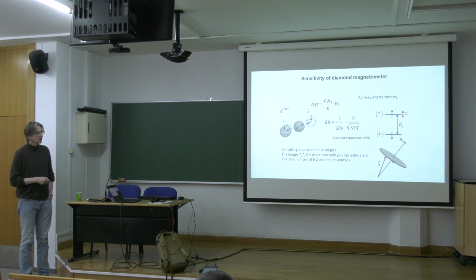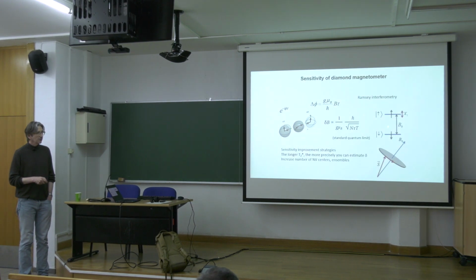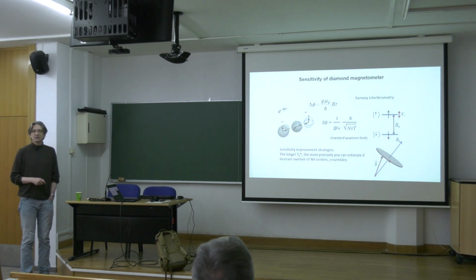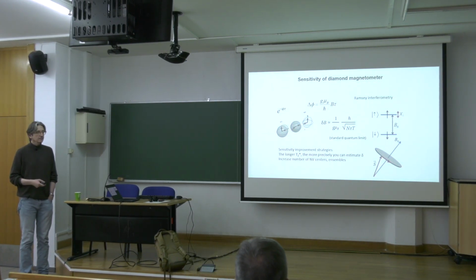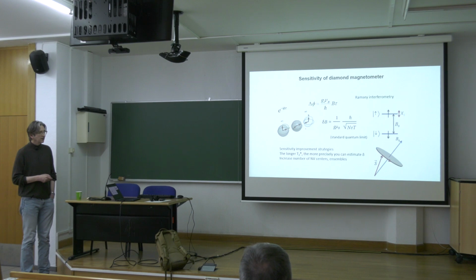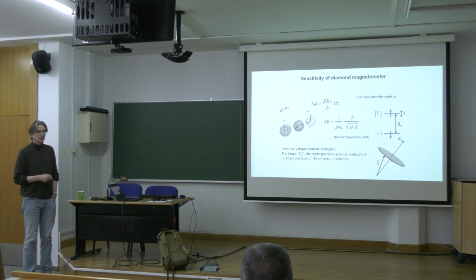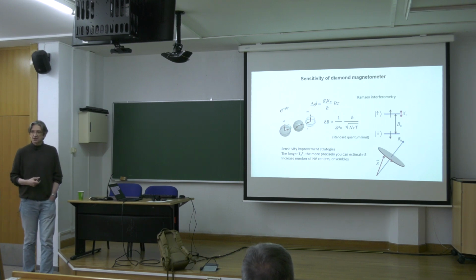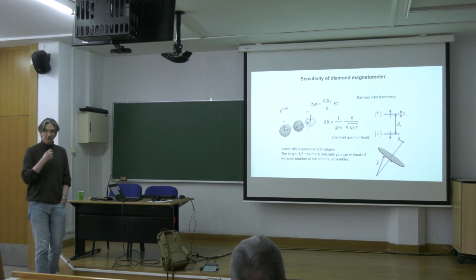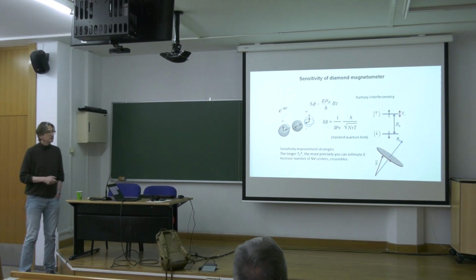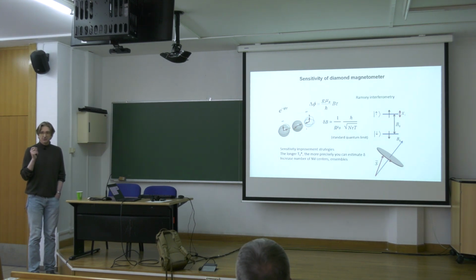So the experiment we do here for magnetometry as a model is exciting a coherent state of a spin, a superposition of spin up and spin down. This state precesses in the external magnetic field, and after some precession time, you measure the phase. The phase is proportional to the magnetic field. So if you know the time, you can measure the magnetic field. But there is always intrinsic noise, and there is also limited time you can acquire this phase. And the smallest possible magnetic field you can measure